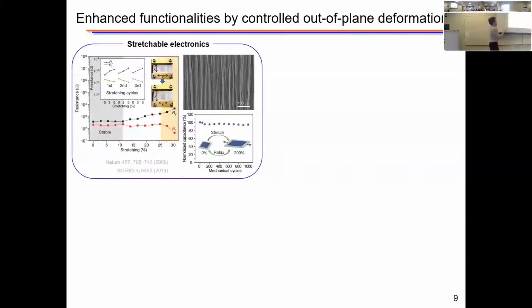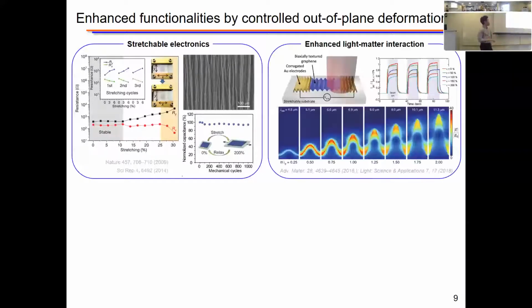For instance, by utilizing topography, we can enhance the electromechanical robustness. So we can improve the stretchability without impairing electrical resistance. Also, we can enhance the light-matter interaction, resulting from the increase in areal density by topography. It's actually a pioneering work done by Professor Kang here. In the below, I'm also showing that theoretically, it's predicted that we can modulate the resonance of the light by changing the topography of the wrinkle itself.